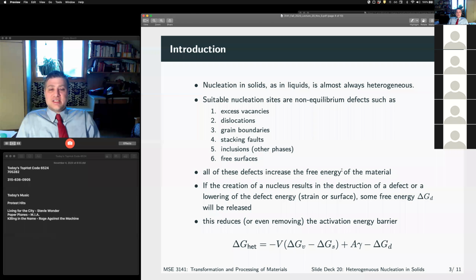Okay. So all of these defects increase the free energy of the material inside, right? Obviously, dislocations come with a large strain and they have an entropy term. The vacancies have an entropy term. Grain boundaries and stacking faults are surface defects. Inclusions, there's an interfacial energy and a volumetric strain associated with inclusions a lot of the time, right? So all of these defects are high energy configurations. So if we can create a secondary phase there, and we do a phase transformation, and by doing that, we eliminate that defect, right?